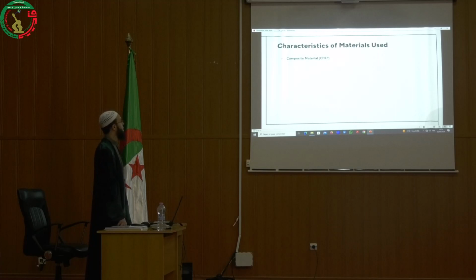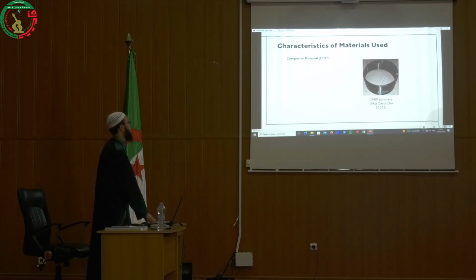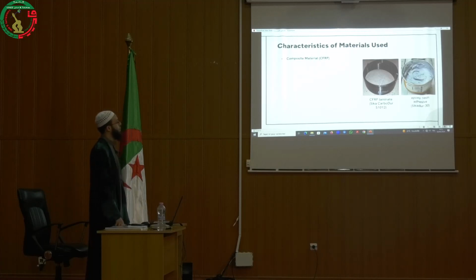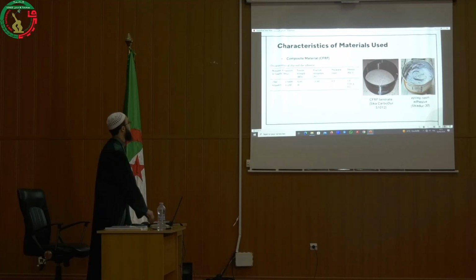With concrete and steel bar reinforcements, we incorporated a composite material, CFRP, for externally retrofitting and strengthening our tested beams. We used unidirectional CFRP laminate from Sika CarboDur S1012, with its appropriate epoxy resin adhesive from Sikadur-30, both with mechanical properties illustrated in this table.